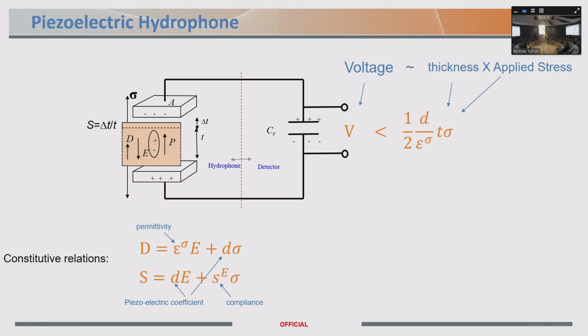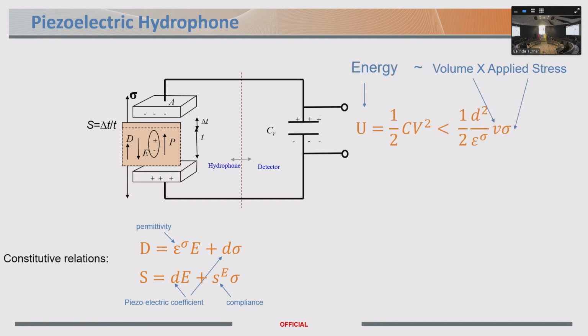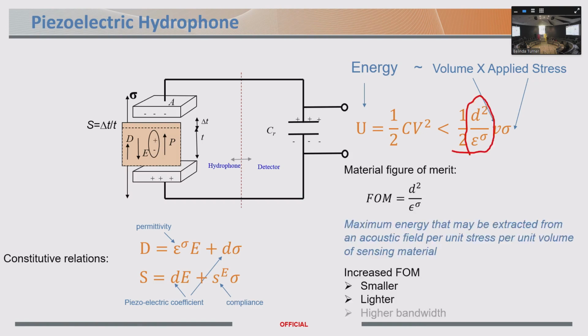The voltage isn't actually a very robust measure of how sensitive a material is. What we're really interested in is the maximum energy that can be extracted from the acoustic field per unit volume of sensor material. And it turns out that when you work that out, just using the relationship between voltage and energy, the maximum energy that can be extracted from the acoustic field, that is what's applying the stress, per unit volume of sensing material, is a material figure of merit. It depends only on the properties of the piezoelectric material. It's this quantity here, which is the square of the piezoelectric coefficient divided by the electric permittivity. Don't worry about that. We just call it the figure of merit.